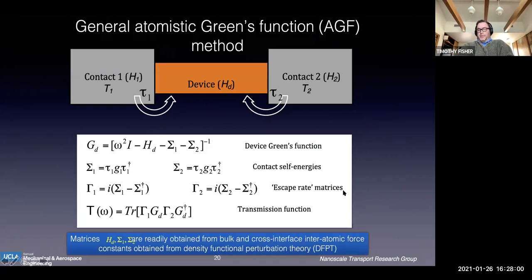All right. So then what we ended up doing is we took a twist on Supriyo's non-equilibrium Green's function method. And I wrote a paper with Natalio Mingo way back when, 20 years ago, on what we call the atomistic Green's function. The difference between them is that the atomistic Green's function is for phonons, whereas the NEGF is typically for electrons. And even though my fonts aren't the same, at the end of the day, with this Green's function approach, what you end up having to do is make a harmonic or Hamiltonian matrix for your device. And then you have to connect it to two contacts that each have their own harmonic matrices. And the bridge between the two become these contact self-energy matrices, right?